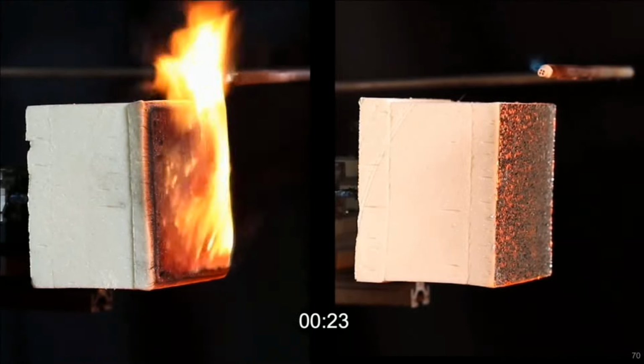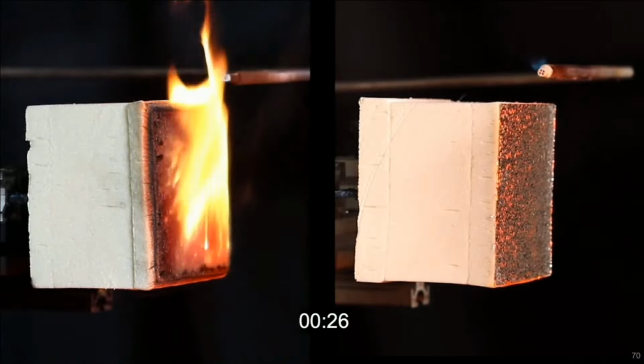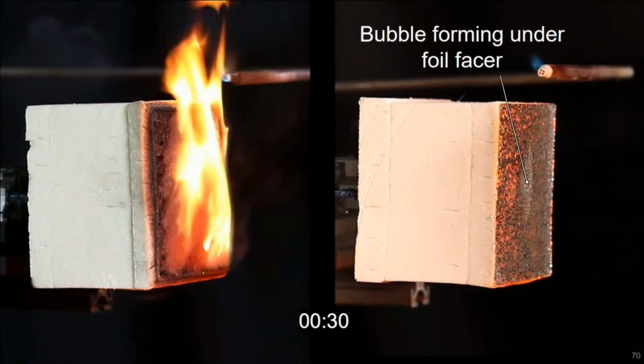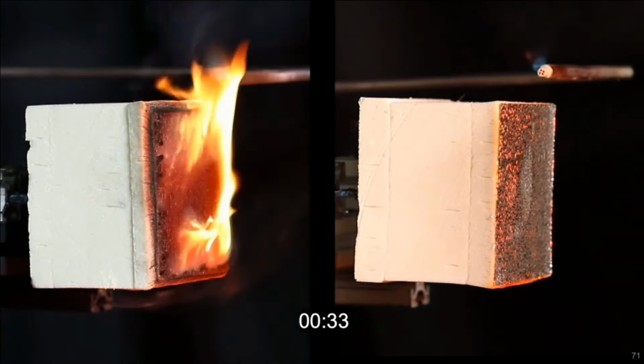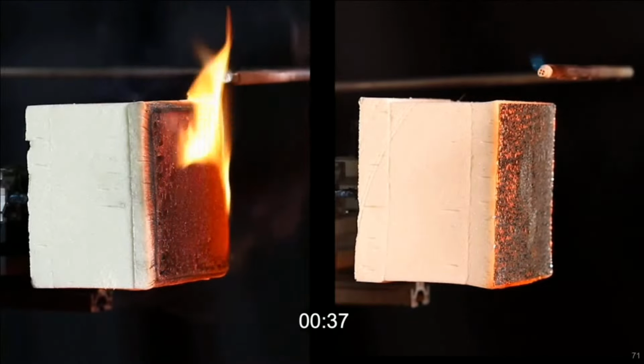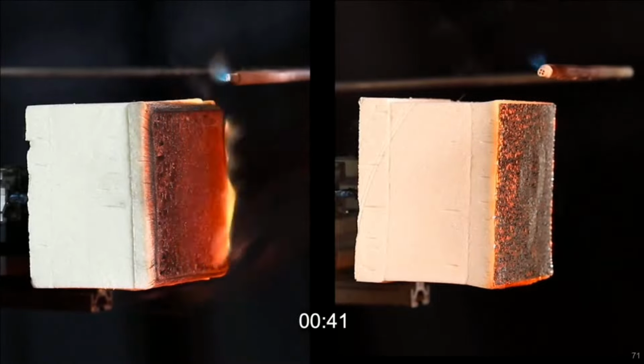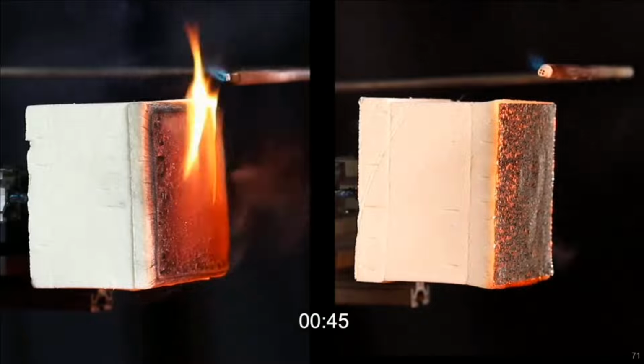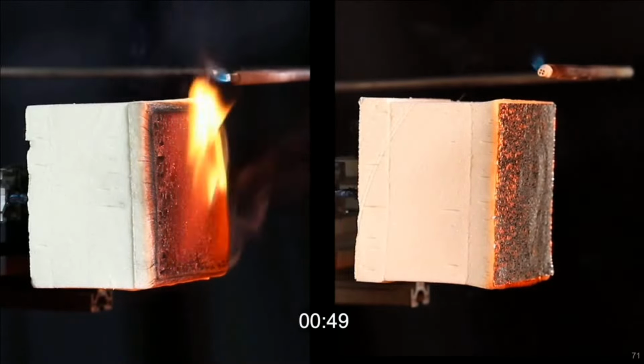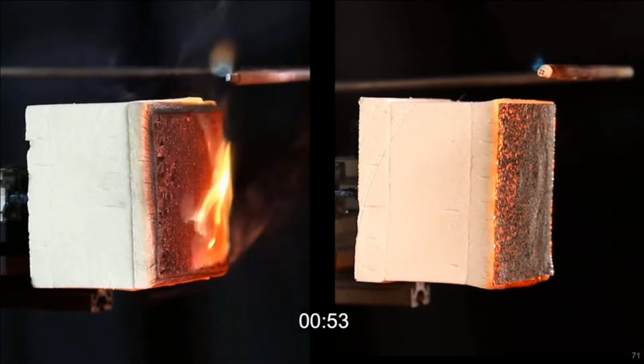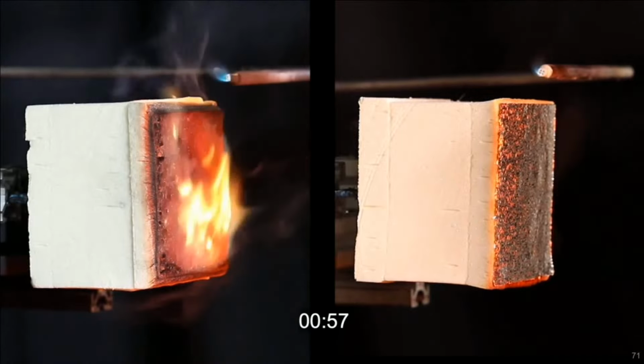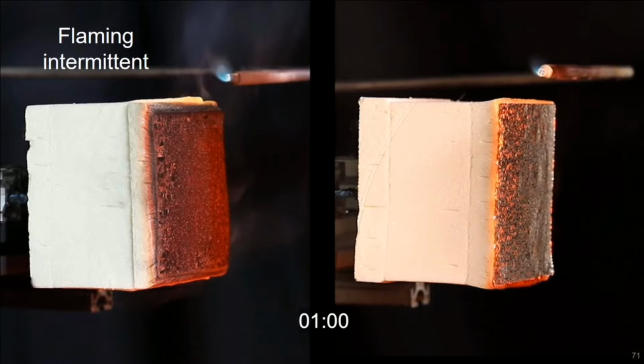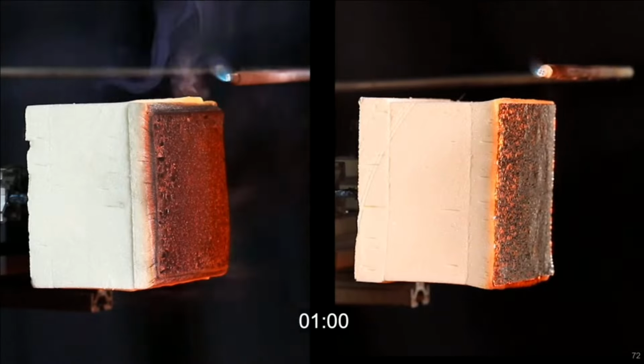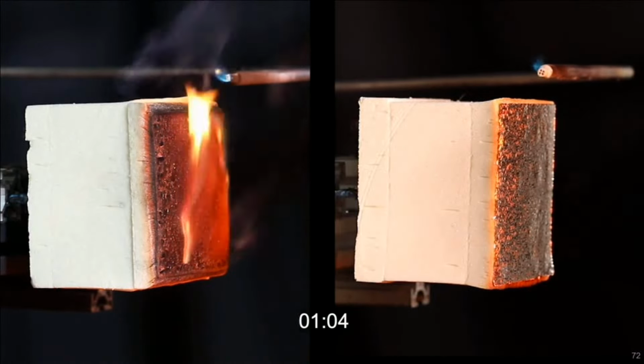On the right, in a moment, we should see the formation of bubbles in the foil facer. So there you can just make out the formation of a bubble in the foil facer. On the left, we'll see the flaming reduce and become intermittent. So there we see the intermittent flaming, and this continues until the char cracks, at which point we see the flaming increase a little bit more.